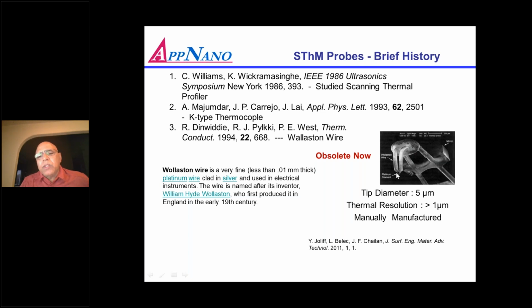People were using this probe even for heating purposes, because this thermocouple is very robust, so you can heat it, not very high, but you can heat it and get a very good thermal conductivity contrast. The big problem was the resolution, and that was one of the bottlenecks. As the size of the features was shrinking, this probe could not keep pace with the technology, so it has now become obsolete and nobody is making those.